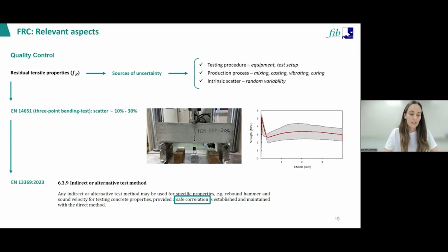In particular, the residual strength of fiber reinforced concrete strongly depends on the amount, distribution, and orientation of fibers crossing the crack area in the test. So for this reason, for example, in the case of the 3-point bending test, the results might have typical scatter between 10 and 30%. An important point is that this variability is usually more significant at material level than at a structural level, where larger resistant volumes tend to produce a more stable global response.